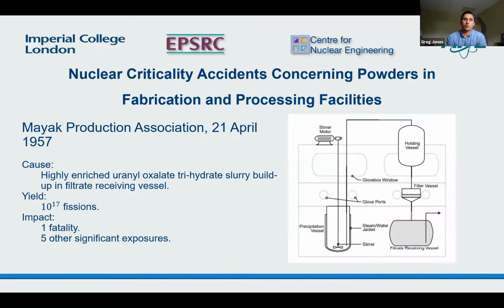I'm just going to highlight a couple of the process accidents that have occurred during the precipitation of powders and slurry-based systems pre-2000. The first one took place at the Mayak facility in Russia, inside a filtrate receiving vessel housed within a glove box that a single operator was working in. In this system, impure uranyl nitrate was introduced into the precipitation vessel that you can see in the bottom left, along with oxalic acid, and they were trying to produce a uranyl oxalate trihydrate slurry. A stirrer was used to keep the mixture homogeneous and stop the slurry from building up at the bottom.